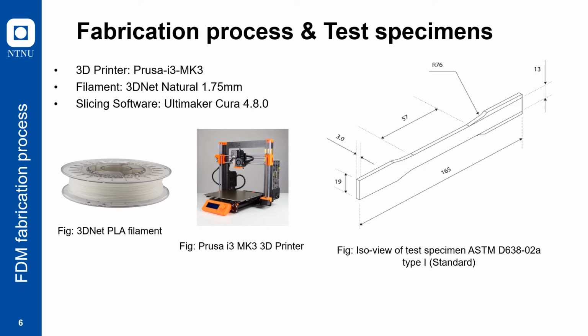And these are the fabrication process and the test specimens. So for the 3D printer, we used the Prusa i3 MK3. It is a very good desktop level 3D printer with very good accuracy. The filament we chose is 3D net, and the color is natural because we have done the literature review saying the colors will affect the mechanical properties. So in order to eliminate this effect, we chose natural color. And for the slicing software, we use Ultimaker Cura. It's an open source slicing software. And for the test specimen, as I mentioned from the last slide, it's standard ASTM.